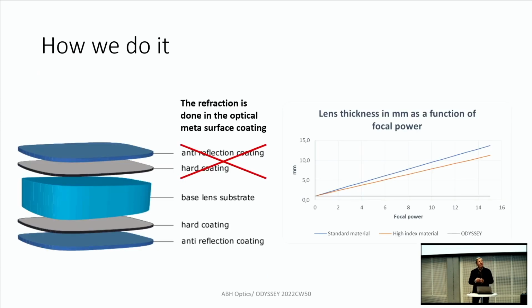The difference between the way traditional lenses are made and the way we make lenses is that instead of having the optical effect in the lens itself, in the lens base, we have replaced one of the coatings on the surface with a meta surface that we can modify with a laser. And this way, the optical effect is just taking place in a layer that's less than a micrometer in thickness, which means that the thickness of the lens is actually determined by the mechanical properties rather than the optical properties, which of course is a good thing.